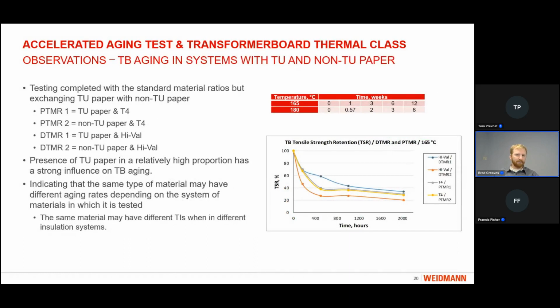Now, in order to try to confirm these hypotheses, another small aging test was completed. For this test, we looked at the same material ratios, the power and distribution. However, we substituted thermally upgraded paper for non-thermally upgraded paper, really trying to see what the impact of the thermal upgrading agent had on the entire system. So we had power with the same T4, TU, and non-TU paper, and distribution in the same way.